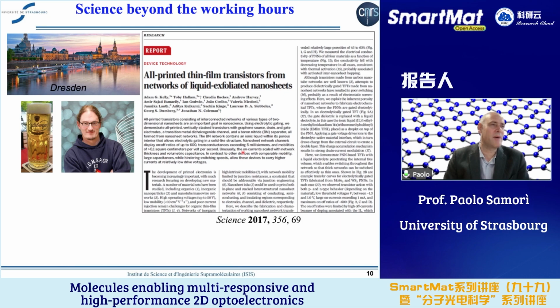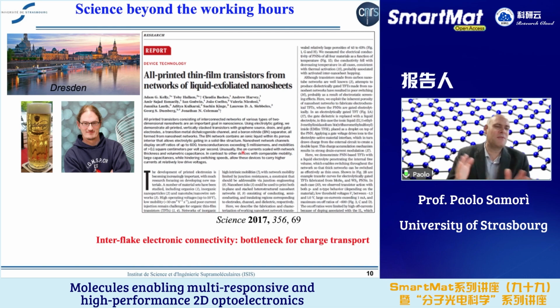That was about all-printed thin film transistors from networks of liquid-exfoliated nanosheets. So he actually took molybdenum disulfide and he printed this. And then I was a bit complaining to Jonathan about the fact that the mobility that he reported was quite low. And he argued that this was due to the fact that in the channel there are a lot of liquid phase exfoliated flakes of molybdenum disulfide, and there is very little interflake connectivity. So the charges don't pass from one flake to the next. And this is the bottleneck for charge transport.